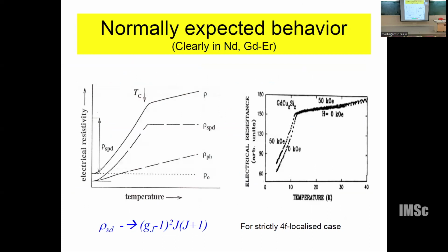Let me look at the electrical resistivity as a function of temperature for any metal. There are mainly two contributions. One is due to the defects in the lattice, called the lattice defect contribution, which is a constant with temperature. The other one is the spin disorder contribution. This is a paramagnetic state. This is a magnetically ordered state. And you lose the spin disorder contribution when the system orders magnetically, when there is an alignment of all the spins. So this is basically what I told you, what de Jongh originally said. This particular number scales with the de Gennes scaling. These are normally expected behavior.